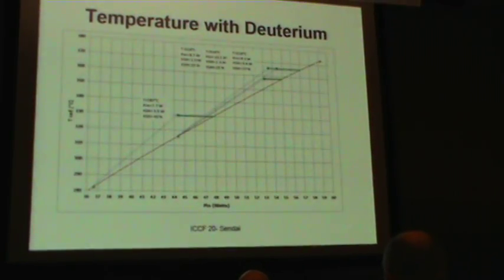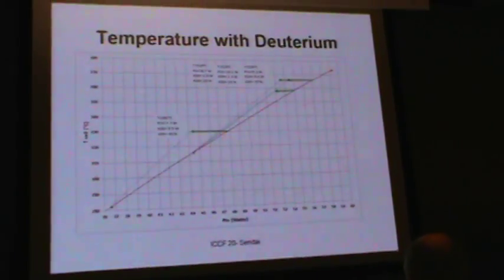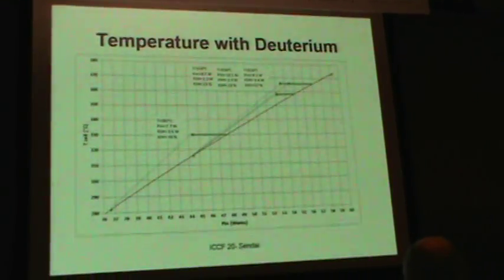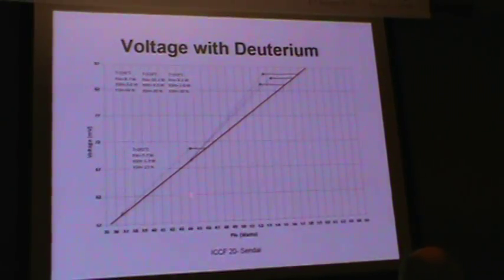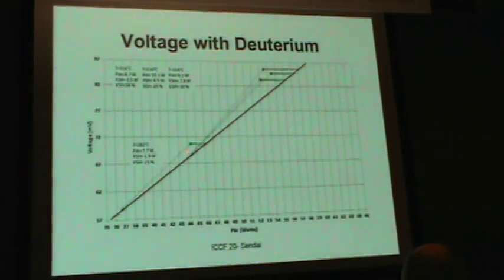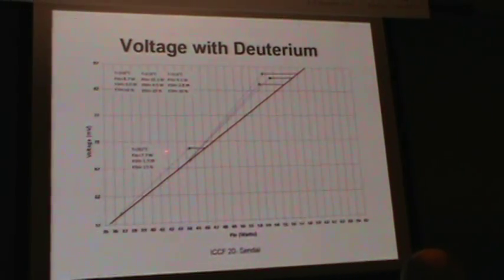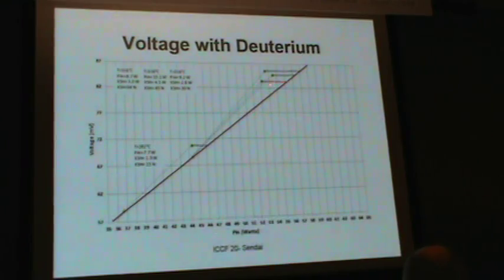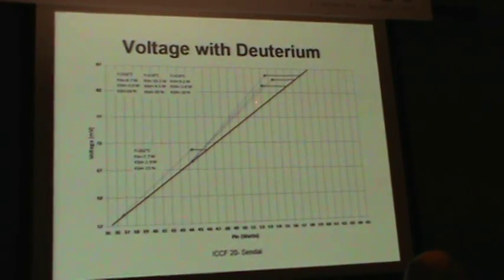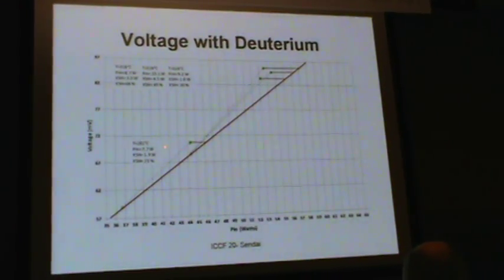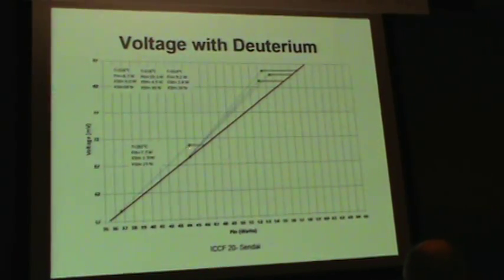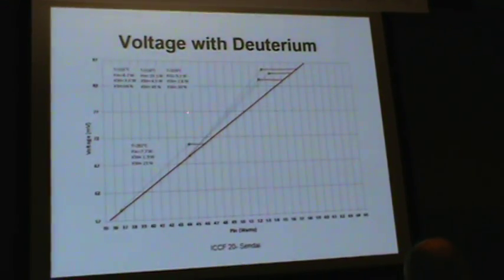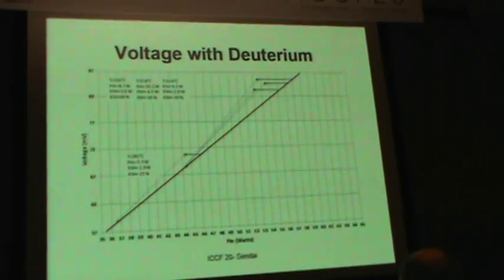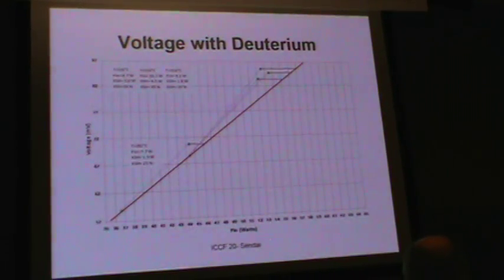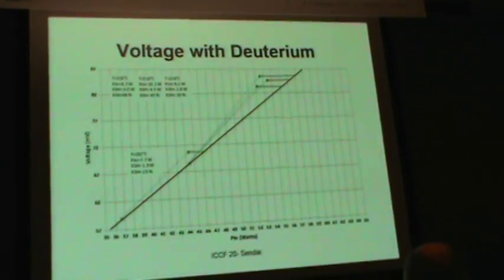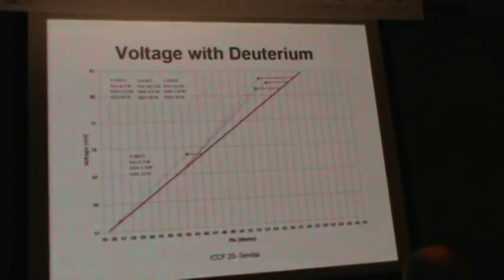Now this is with the temperature. I can do the same thing with the voltage, and they give pretty similar results. I mean, it's not exactly the same. You have 25 instead of 50, 45. Here it's slightly higher. The average is about 33%. This has not been optimized at all. My calorimeter is not well suited to work above 400, 450 degrees. I have to modify it to improve that. But it worked pretty well.